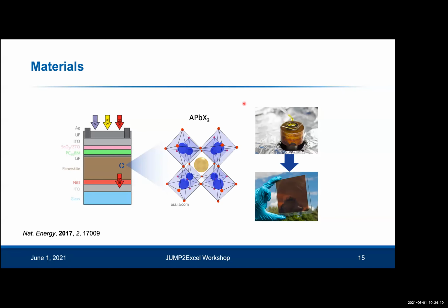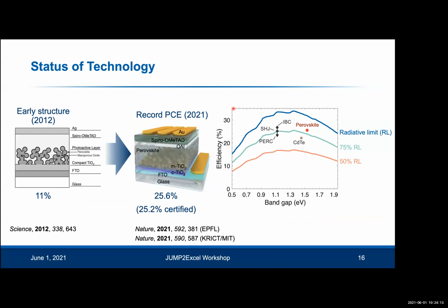So this slide summarizes the history of the development of this technology. It was first reported in the solar cell in 2009 by a Japanese group, and they were thinking about this material as an alternative to a dye in a dye-sensitized solar cell. And this was picked up by a group in Oxford who made devices with this structure here. So you can see there's still this mesoporous scaffold, which is from the dye-sensitized solar cell, but this time using a solid-state hole transport material instead of a liquid electrolyte. And suddenly the efficiency shot up from about 4% to 11%. And this was back in 2012. And that's when a lot of people started paying attention to this technology.